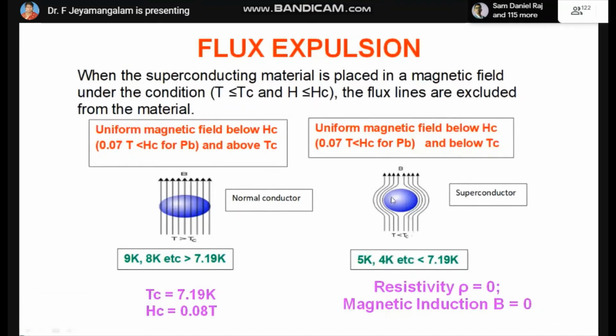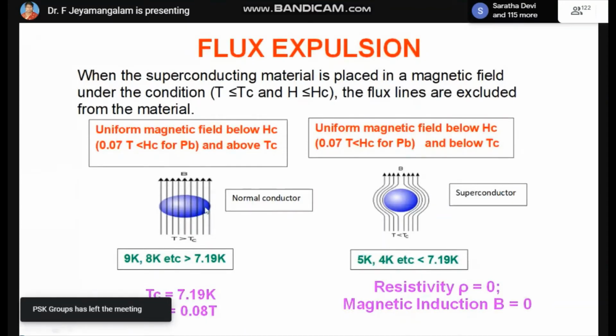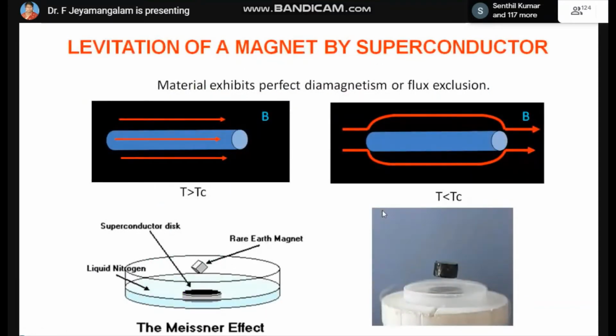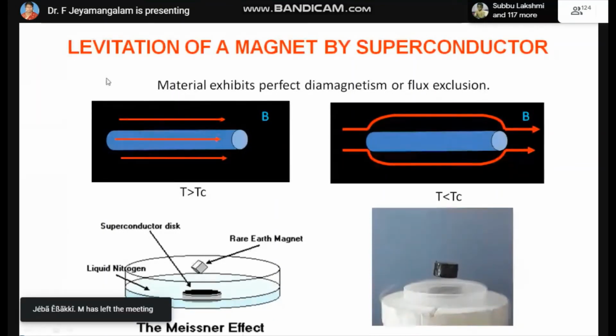So the flux lines are expelled out. When it was a normal conductor, the flux lines were penetrating into the lead ball, whereas when the temperature is reduced, the flux lines are expelled or thrown out because the resistivity becomes 0 and the magnetic induction becomes 0 inside the superconducting material. I have another picture to explain this Meissner effect to a greater extent. This principle of the Meissner effect is used in the levitation of a magnet using a superconductor.